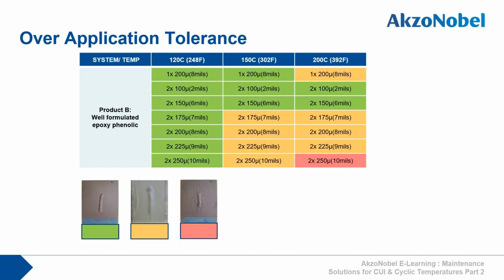Now, if the panels are heated to 200 degrees Celsius, we see a mixed picture. Initially, there is cracking around the weld, but then we see good performance for 2 schemes. Again, likely because of lower solvent entrapment in each coat, but then cracking around the weld is seen for higher DFTs, with 2 times 250 microns scheme cracking badly.